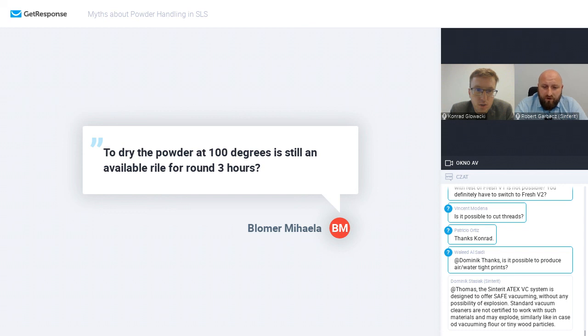To dry the powder at 100 degrees Celsius is still available for around 3 hours. Yes, I think 100 degrees, stirring it from time to time, leaving it for 2 or 3 hours, it also does the job.